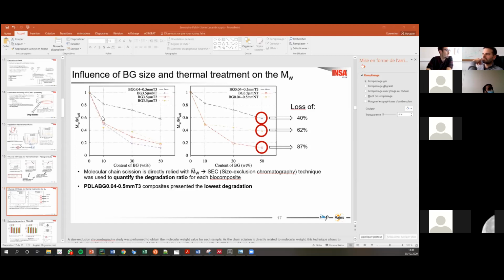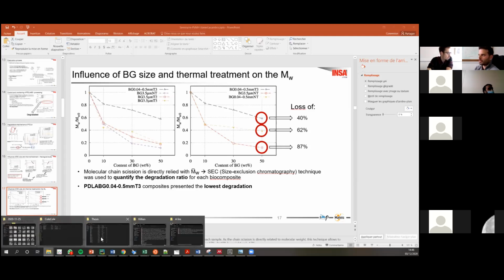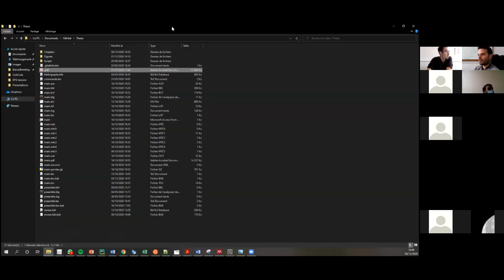Showing the average is more related to the degradation, no? I mean, both. Yeah, it's good like this. I was just curious about whether you create very small chains or possibly you may have branching also, but from the rheology you show, apparently it's more chain scission. So I was just curious about the distribution if you had it, just to have a look at it. It's very clear that molecular weight decreases and viscosity decreases. But I think there is no problem on this.